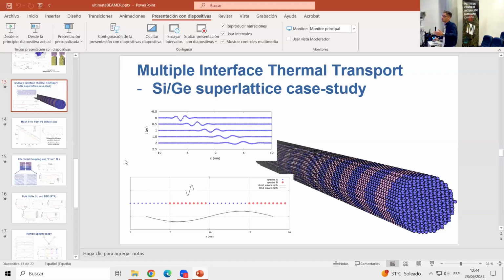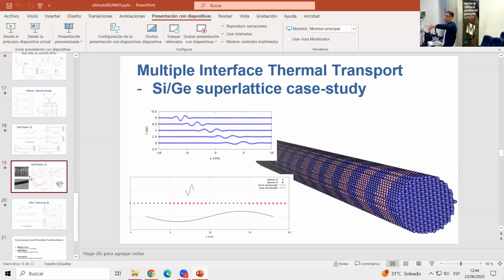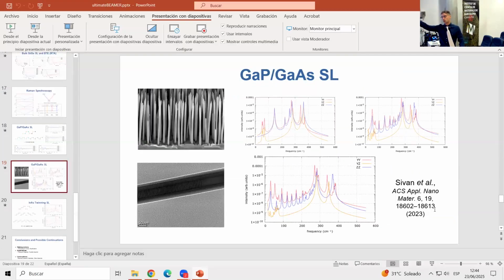As soon as it doesn't really matter, you know perfectly that the number of peaks, well, okay, this is Raman, so there is also the optical thing, but the number of phonon modes really strictly depends only on the number of atoms that you have inside the primitive cell. So you know that you will see at least these many peaks, and then the selection rules may switch off some of them. Some of them will not be Raman active. They will be optically irresponsive somehow. But still, you cannot say from these where the position of the minima is. You will know that there is going to be a minima. So there is no direct correlation.